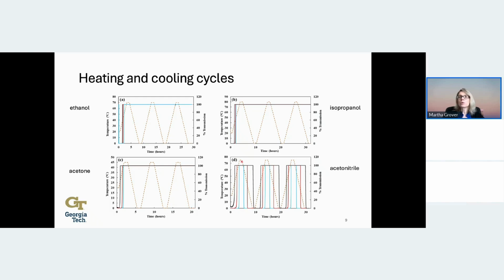And then upon cooling, we see crystallization occurring at the 3 different concentrations at pretty similar times. You can see the pattern here of the times of crystallization are not so different, even though crystallization is a stochastic phenomenon, primary nucleation. And so you might not be surprised if these were at different times, but in fact, they look very similar. But we would expect to crystallize the same form in all 3 cooling cycles because in all cases, the material was fully dissolved.